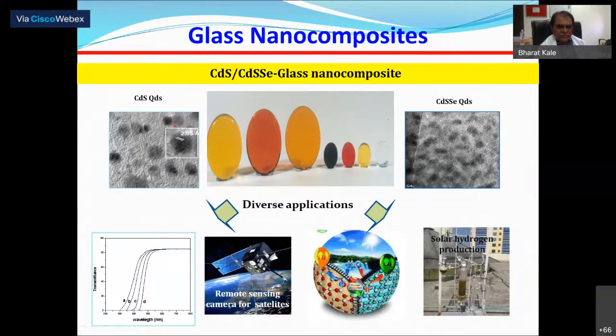This is typical glasses, the cadmium sulfide image. Initially it is transparent, then you have cadmium sulfide as 2 nanometer, 5 nanometer, and as the size changes, their color changes when their optical property changes. So we have application in the optical cutoff filters from 400 nanometers to around 800 nanometers for electronic application, which were imported. Now we have indigenized.